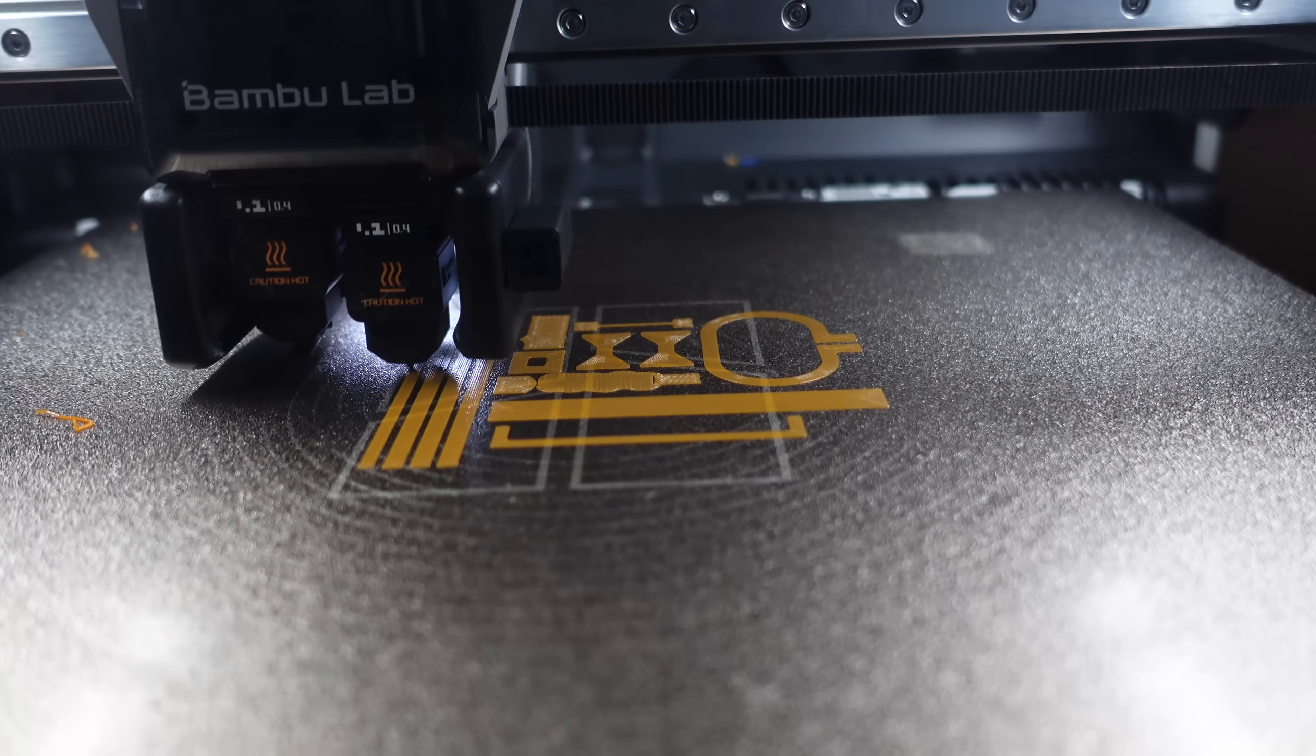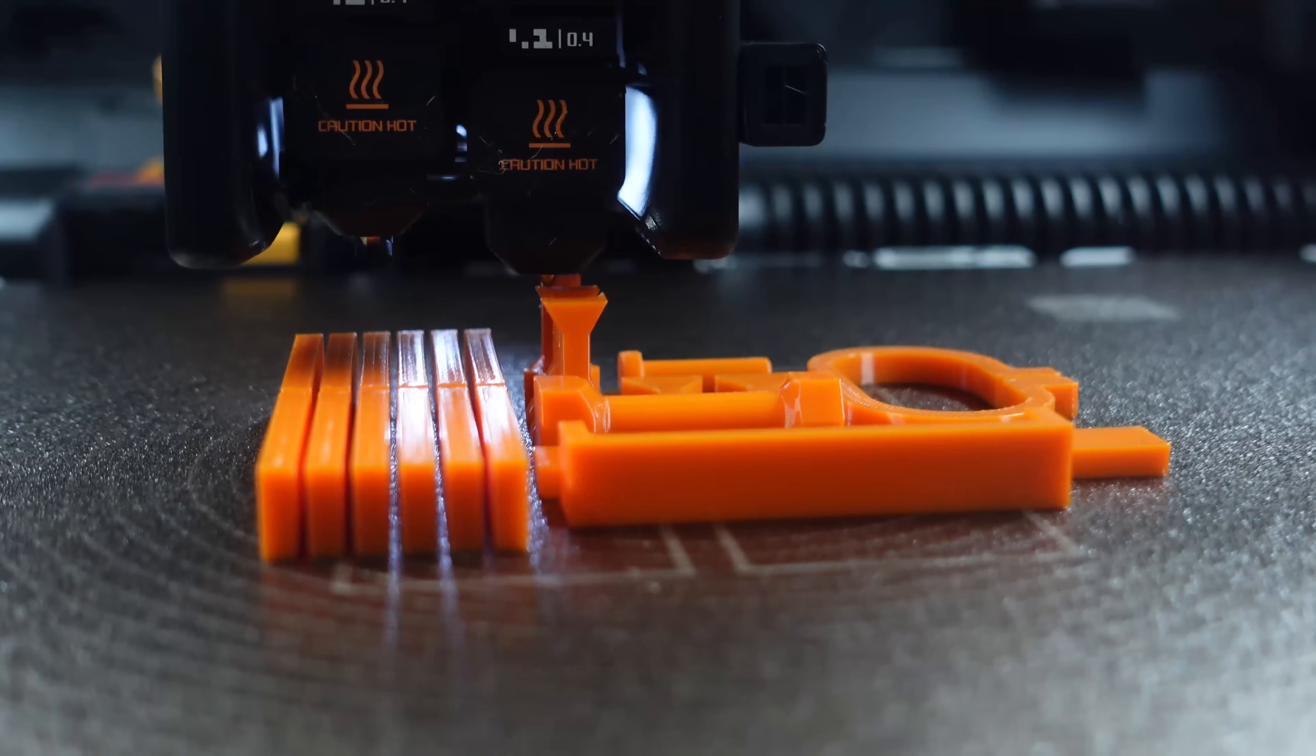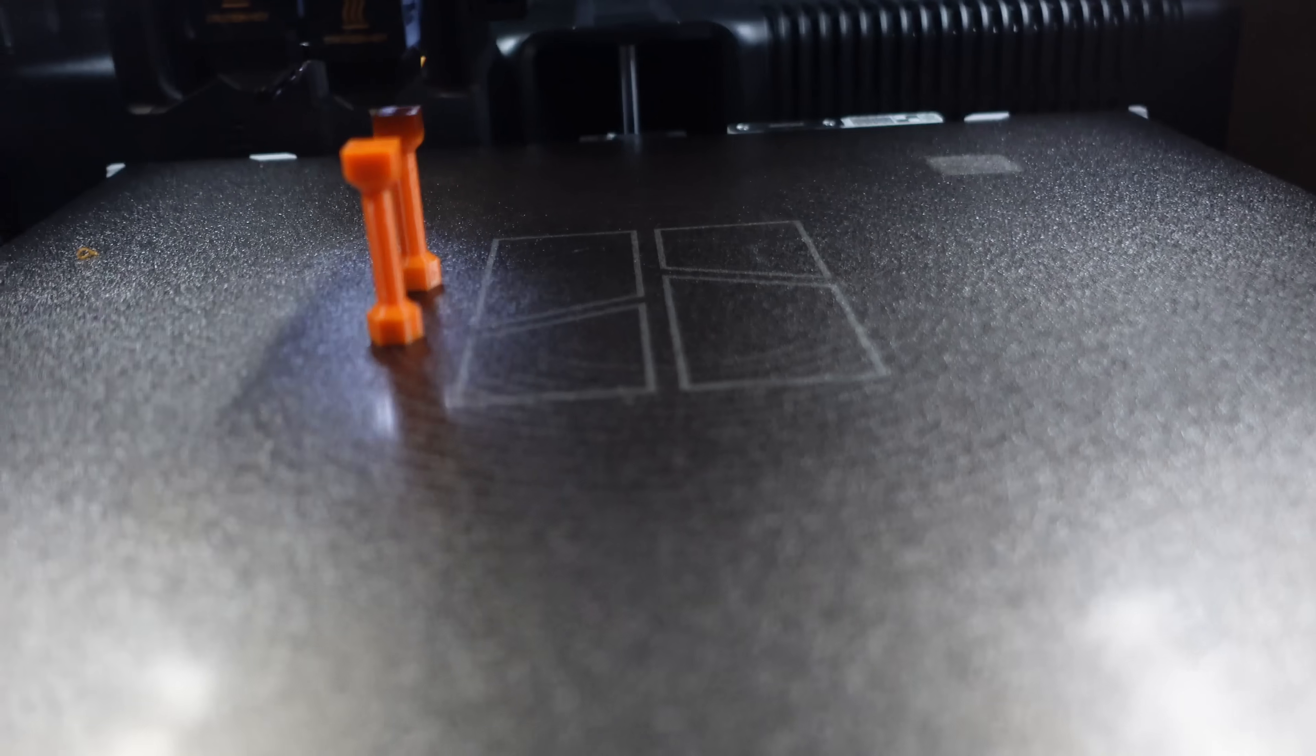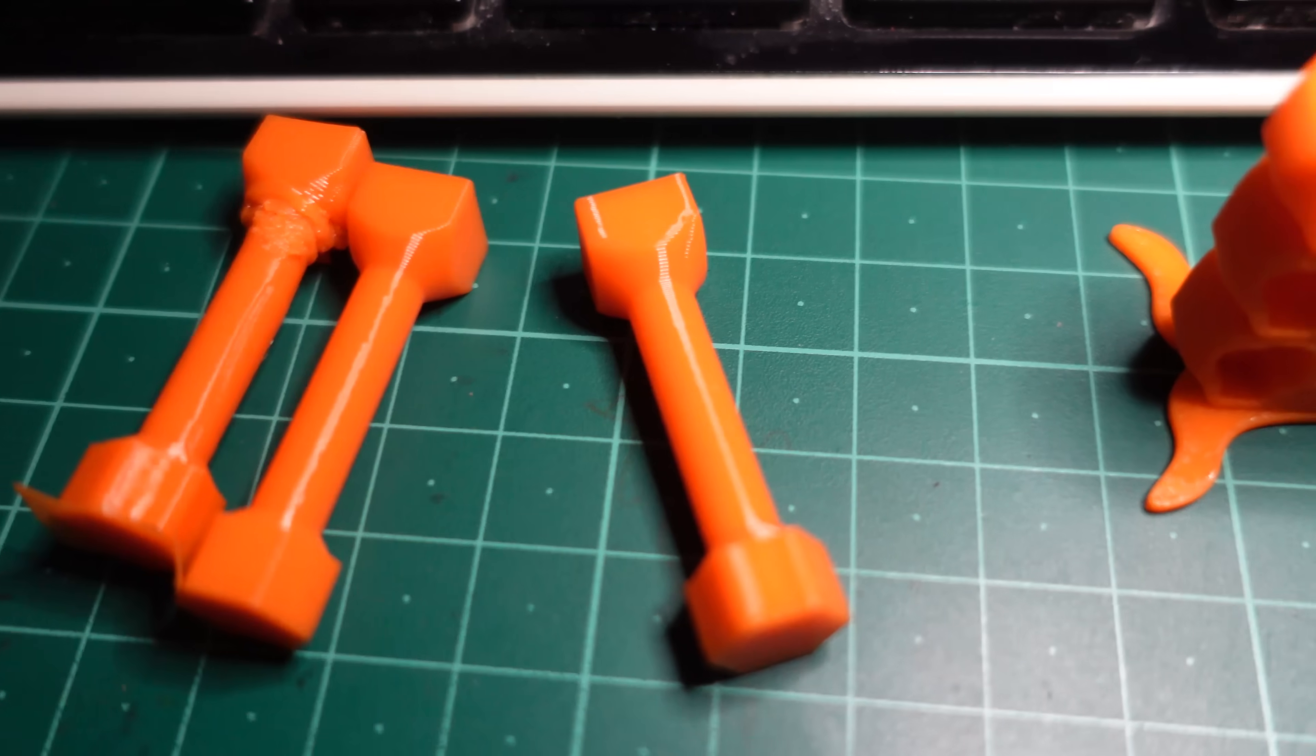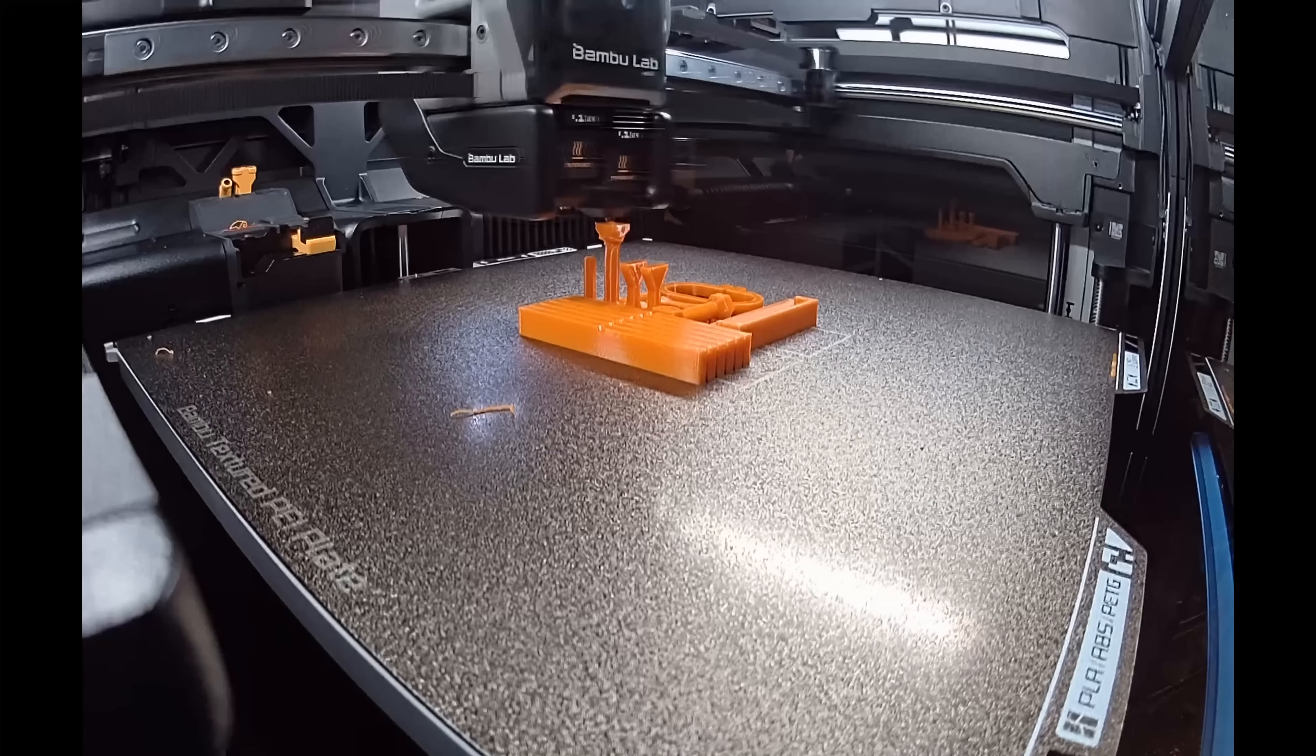Start of the printing is great. This is still the first layer. And by now almost all horizontal test objects are finished. And look how fast it is printing the vertical test objects. Bridging region is great again. And only with the last test object I had this problem. The layer printing time was too short. I increased the maximal part cooling back to 50% and I printed two at the time. And this time it came out perfectly. This was the only change. And this is the sped up timelapse video of that original printing. Everything was fine and only with that one last test object I had this problem.